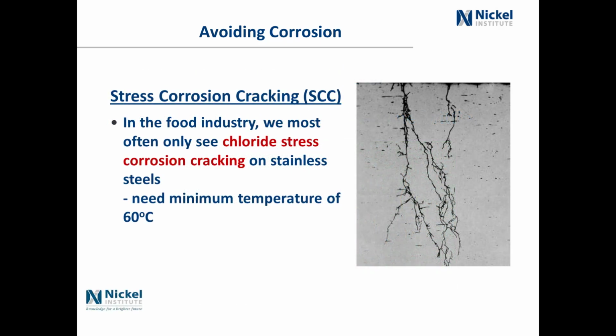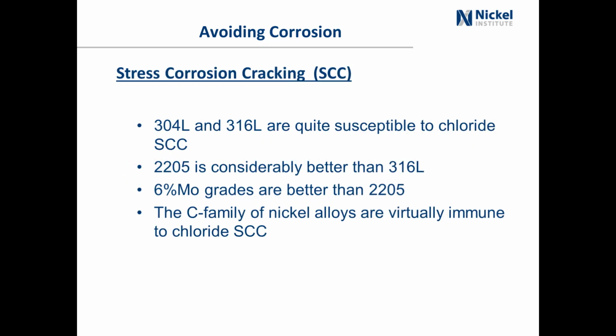In the food industry, if you were to see chloride stress corrosion cracking, which is a multi-branched crack, you'll usually see it because it's related to chloride that's present in the environment, and typically you need a minimum temperature of 60 degrees C to see chloride stress corrosion cracking. With regards to stress corrosion cracking, 304 and 316 are quite susceptible to chloride stress corrosion cracking. 2205 is better than 316.